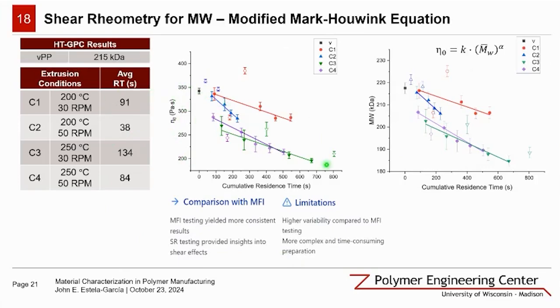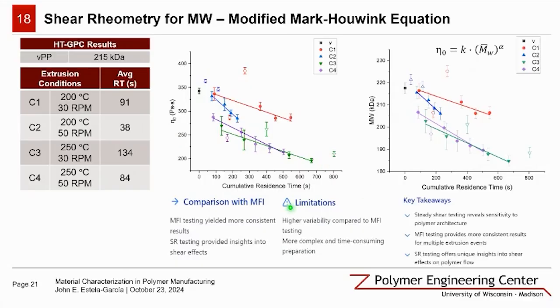When we compare these results to MFI, there are in fact higher variabilities in the rheometry results, but these variations could simply be caused by the innate sensitivity of this test to the polymer architecture or the sample preparation method. Nonetheless, we do see similar trends as appreciated by the MFI testing.